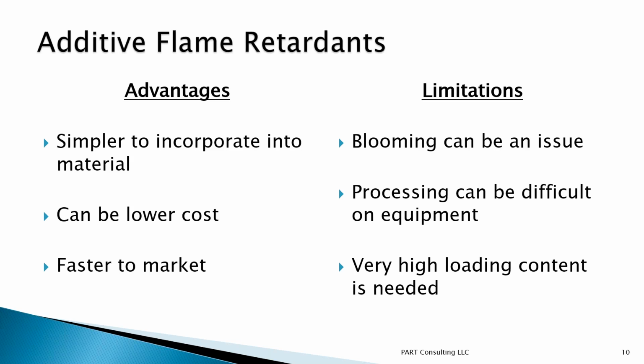Additive flame retardants are simpler. They can be lower cost, not necessarily all the time. And the main advantage is that if you have a formulation, it's much faster to market if you have an additive flame retardant in there. The limitations are blooming. Processing can be difficult on the equipment. Some of these flame retardants can be corrosive, can be abrasive, and they can affect wear and tear on equipment. Also, the disadvantage to additive flame retardants is that in some cases, depending on what you're using, you're going to have very high loading levels. It isn't as efficient as reactive flame retardants.